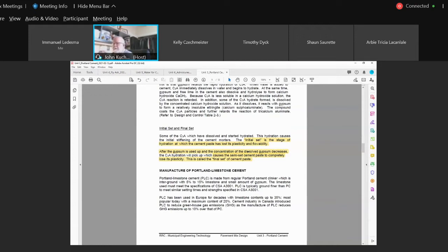And already, once water and cement come together, okay, the water can come just from the aggregates. In other words, you may have damp aggregates, drop them onto a scale, add the cement powder at the batch plant. Well, that cement and water has now come together, but hydration is starting, even though you may not have added mixing water.